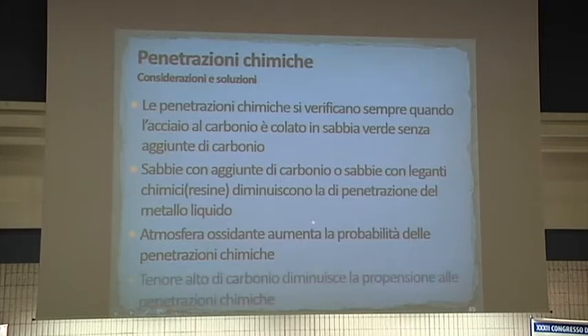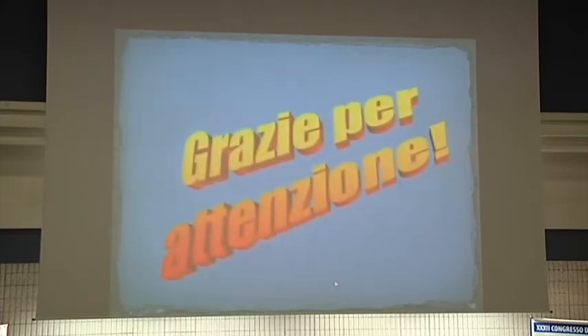So how do we solve this problem? For steel, for example, we add carbonaceous materials in the mold that will have carbon that is oxidized by the mold, so we don't oxidize the steel. And we experimented with an oxidizing atmosphere, and that increased the probability of penetration. And if we have higher carbon in steel, that also decreases the probability of penetration. Mille grazie.